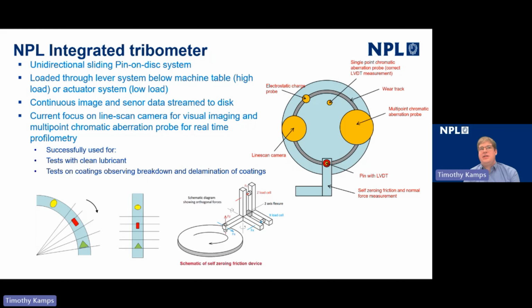This information is continuously streamed to the disk, and that effectively means that this arc of the wear track that occurs around the disk is actually manifested as a rectangle, and the image at the bottom left shows how the camera systems, which are both line scan cameras, acquire data as the disk rotates, and this is saved as a rectangular image. This system has been successfully used for clean lubricants, and we have